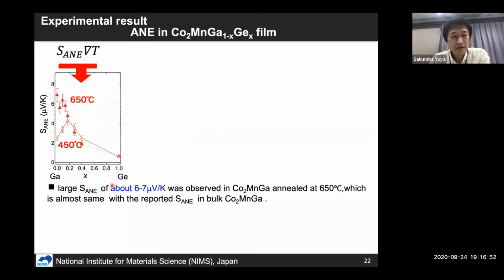Okay, here I show the gallium germanium composition dependence of the thermopower of the anomalous Nernst effect. As you can see, interestingly, the thermopower of the anomalous Nernst effect drastically changed from the B2 disordered structure to the L21 ordered structure. And in this experiment, we observed the highest thermopower of ANE, 6 to 7 microvolt per Kelvin.